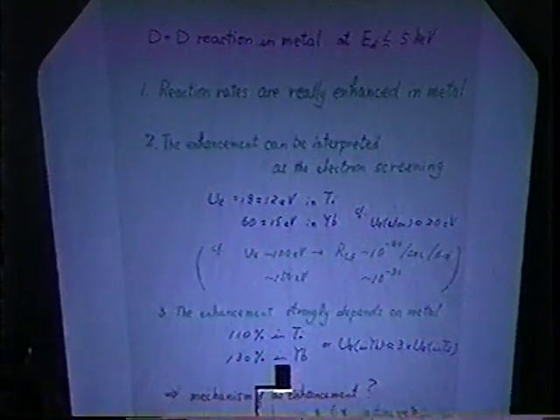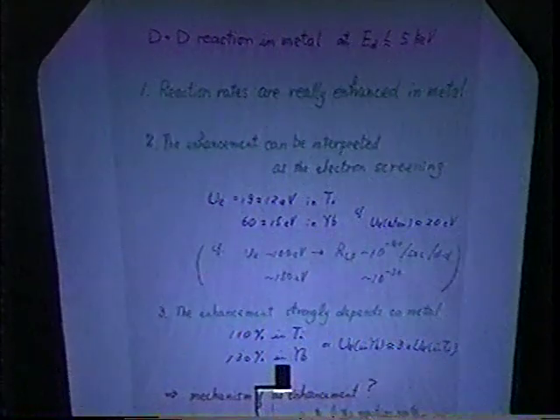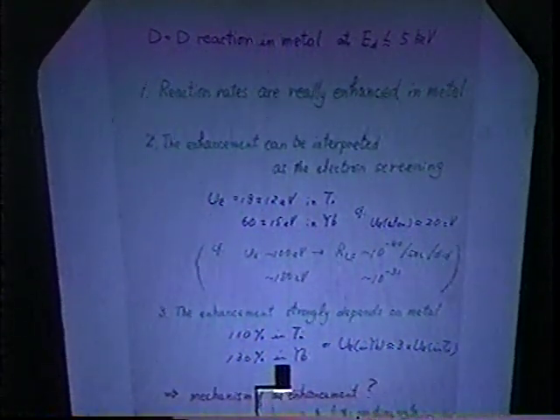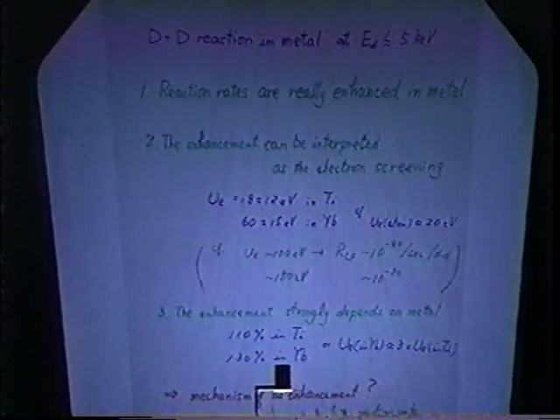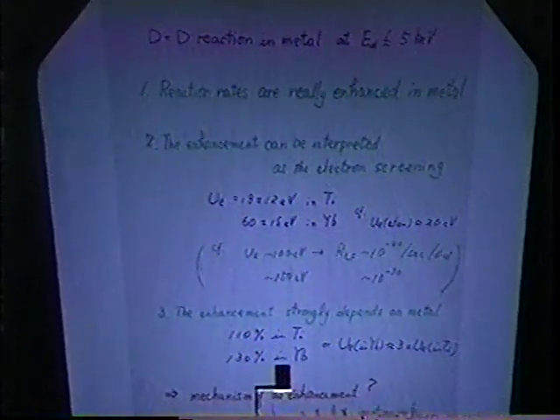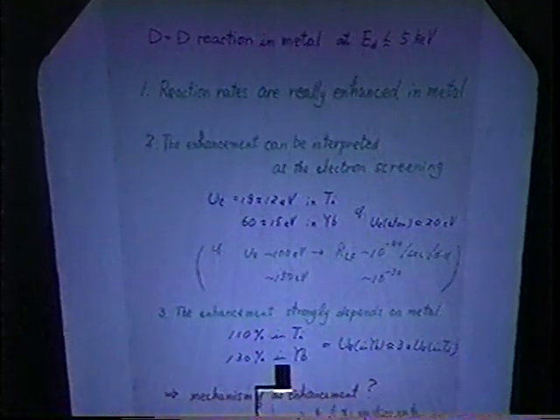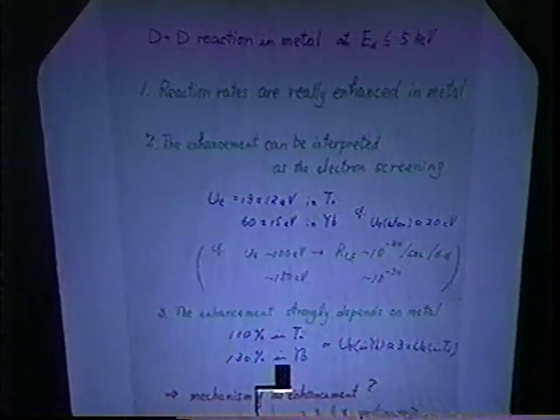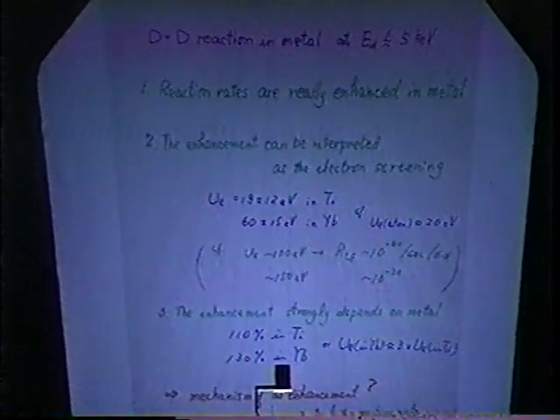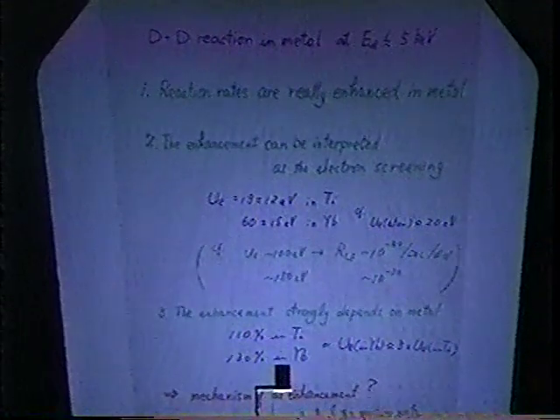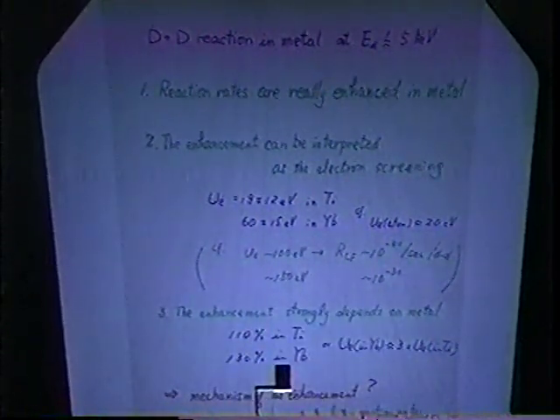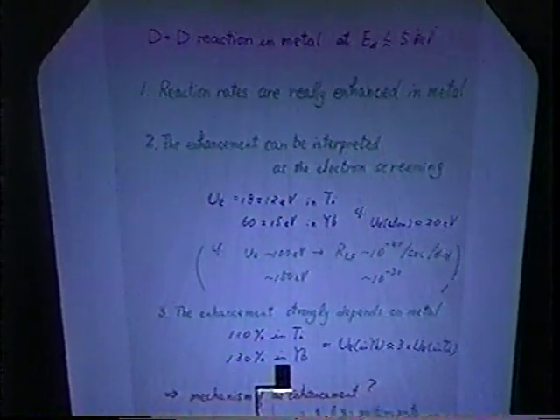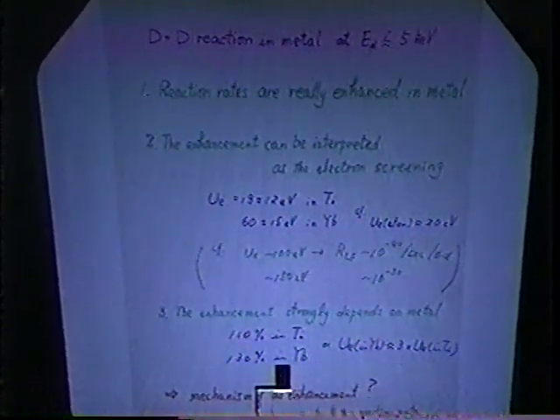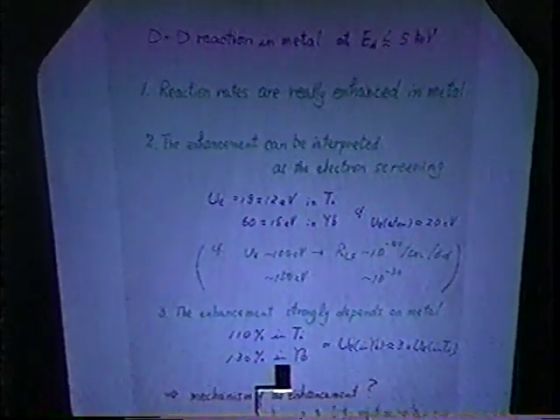So I'll summarize my talk. We studied the D plus D reaction in metal at incident energies lower than 5 keV. And we saw the reaction rates are really enhanced in metal. And this enhancement can be interpreted as electron screening. If we do such an analysis, we deduce the electron screening potential is something around 20 eV for titanium metal and 60 electron volt in the ytterbium case.